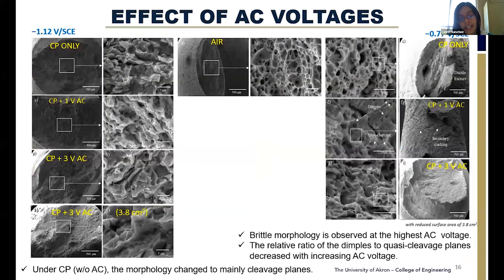After that, we analyzed the fracture morphology using the SEM. And we see here a comparison of the two cathodic potentials and the sample in air, which is basically ductile. We see the reduction of area is clear and the microvoids are showing a ductile fracture mode. However, with the sample at -1.12, for all of them, even with AC voltage and without AC voltage, the morphology is similar to quasi-cleavage planes, so it's basically brittle for both.